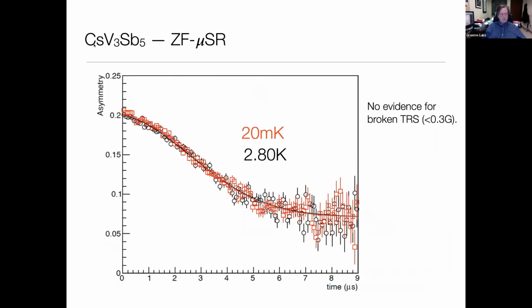So the bottom line in cesium vanadium 3 antimony 5 is that in fact there is no broken time reversal symmetry. The spectra at 20 millikelvin, our base temperature, and 2.8 Kelvin are exactly the same. And so within the degree to which we know how small our fields are, which is about a third of a Gauss, we can say there is no evidence for broken time reversal symmetry in this system. So we don't break that symmetry in this material.